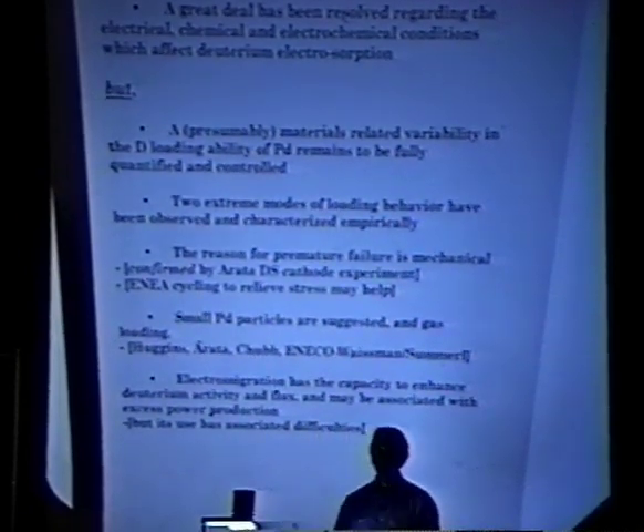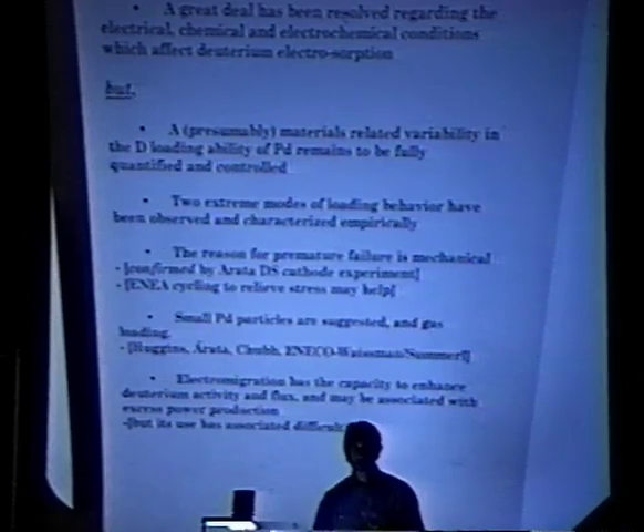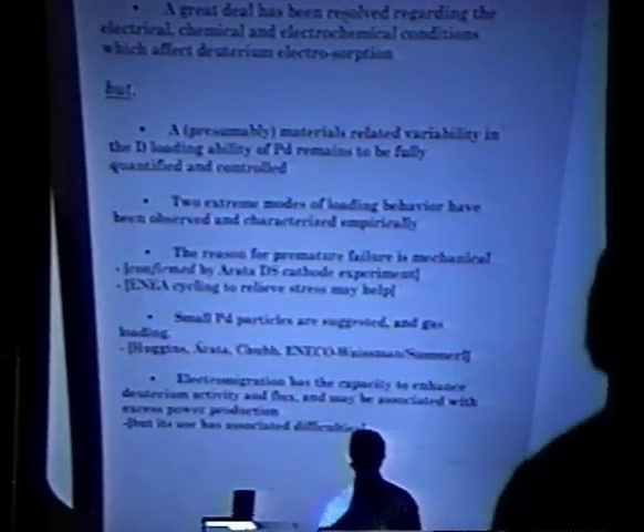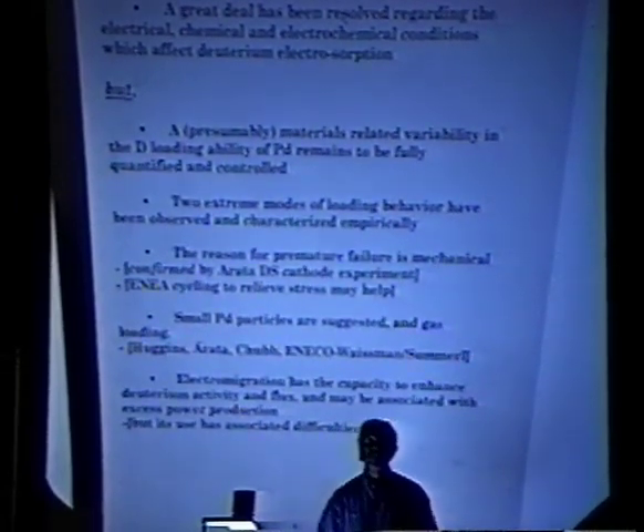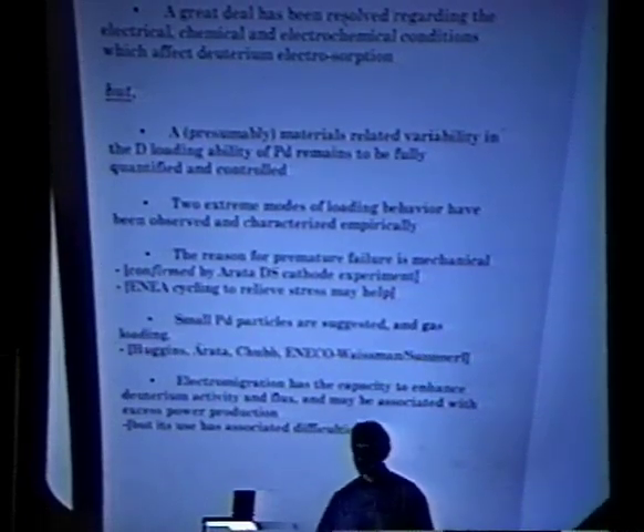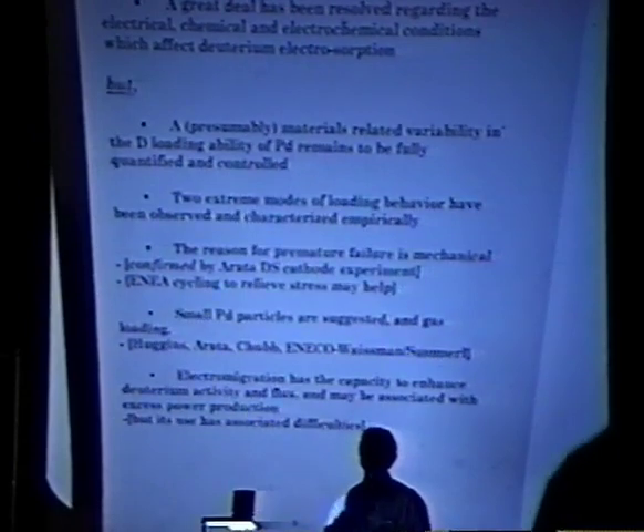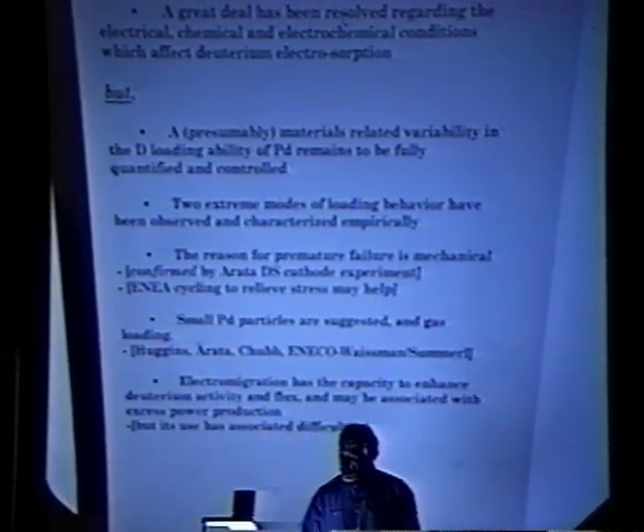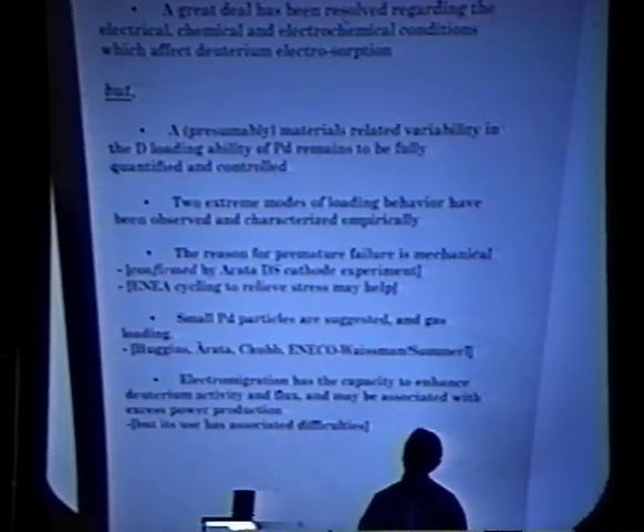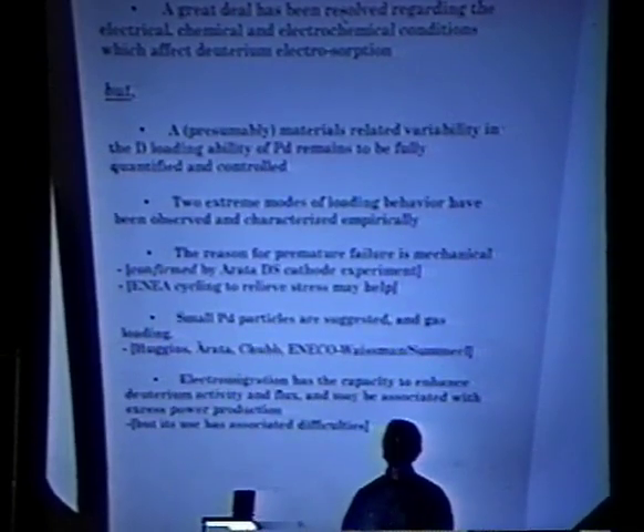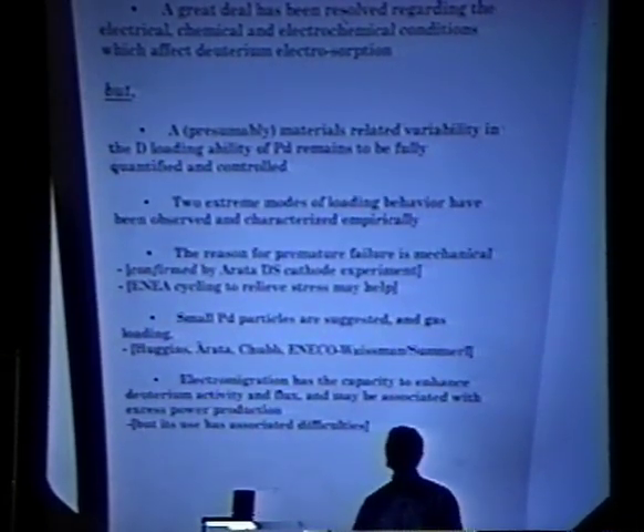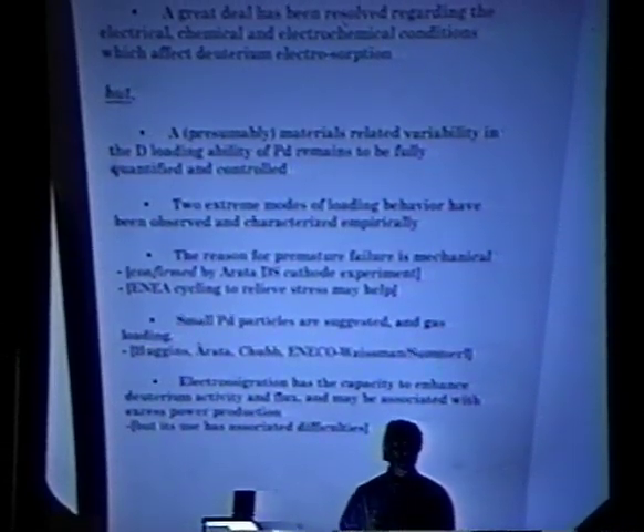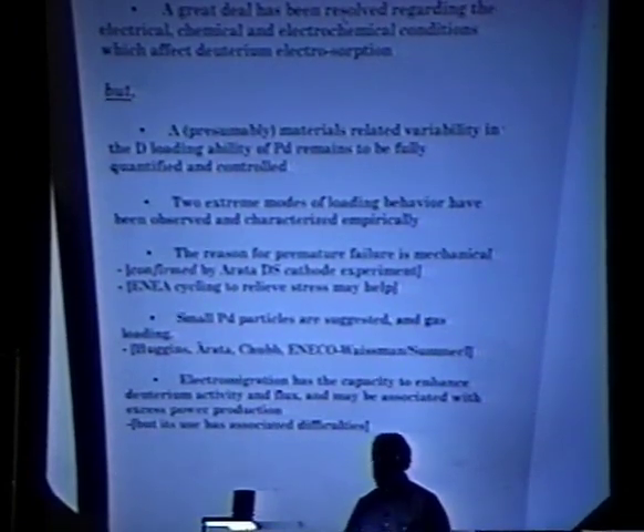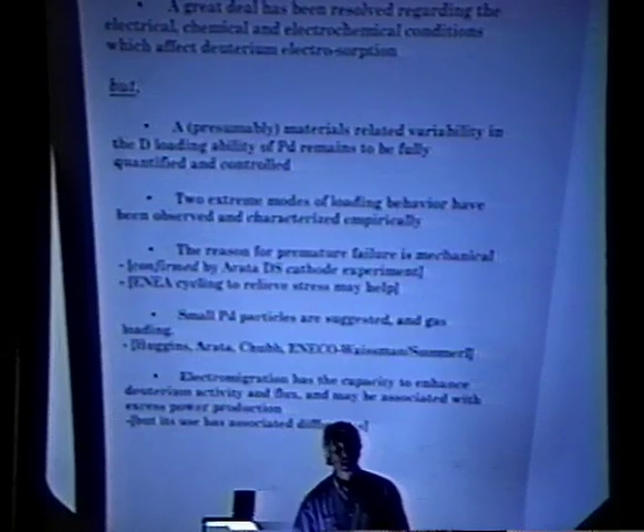I submit, although I haven't proved, that this variability is entirely mechanically associated. It has to do with the yield strength of palladium in its impure and defective state, and in the presence of deuterium and the cold work introduced by putting deuterium into the cathode. We have characterized two extreme modes of behavior, the log linear reduction in resistance, which sometimes yields extraordinary values of loading, extraordinary values of chemical potential, and mostly, but not always, anomalous excess heat. I'm claiming that the reason for premature failure of my mode B response is mechanical disruption.